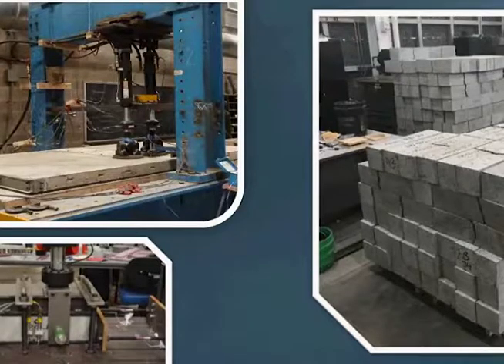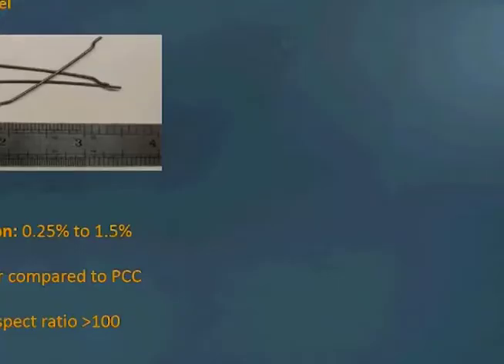So now I covered a little bit of the literature and what we are actually doing. In the laboratory study, this is just an introduction picture. We reviewed what other people are using and what parameters of the fibers they are looking at. Okay, so we saw a typical volume fraction, in field and laboratory studies. People use from 0.25 to 1.5% volume fraction. When I say volume fraction, it's the volume of the fibers with respect to the volume of the concrete.